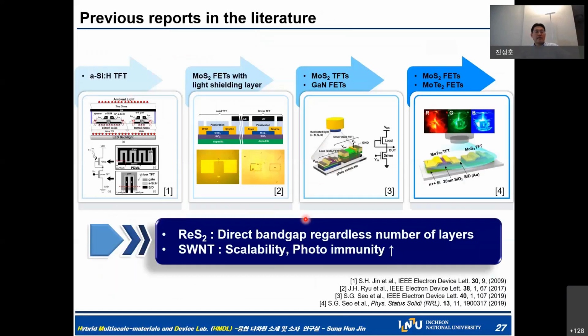Here is a summary of the previous reports in the literature. Basically, the starting point is 2009 in Electron Device Letters, when photosensitive inverters were achieved by amorphous silicon technology. That technology was then extended toward molybdenum disulfide. In order to avoid the light-sensitive silicon layers, we can also adopt an N-type gallium nitride, which has a very high energy band gap, in order to achieve low sensitivity outside the exposure region. Another key point, as compared with the N-type depletion load or enhancement load, is that applications also need much lower power consumption, using MoS2. That is one of the research achievements up to now.